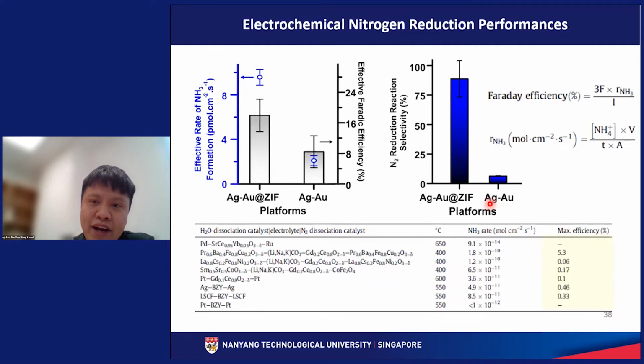So next, by quantifying the amount of ammonium present, we are able to determine two important figures of merit. One of which is Faradaic efficiency. Okay, so this is basically the percentage of electron supply to the system that can be used to create ammonia. So the higher it is, of course, the better the electrochemical system is. So second, we have the rate of ammonia generation. So from this table, we are able to see that the rate of ammonia formation is relatively similar compared to what is in the literature.